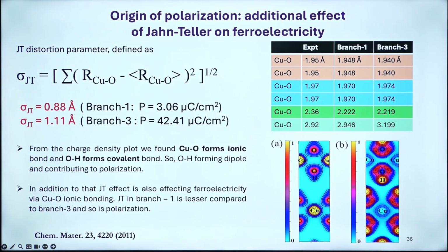I will not say that's the only thing which is responsible, apart from freezing the phonon mode and getting a new space group. Of course, this is a structural phase transition from a paraelectric to a ferroelectric, and the Jahn-Teller effect also has an added advantage. Copper is in the 2+ state here. So that also we concluded.